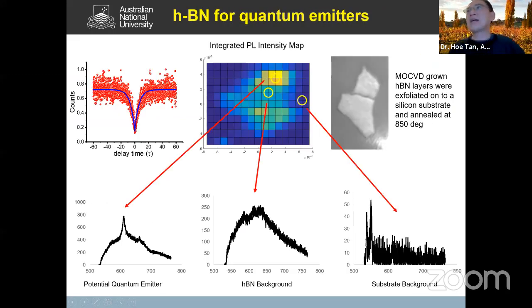But what we also discovered in collaboration with some colleagues from University of Technology Sydney, is that this impurity emission is actually not too bad. You know, you look at here, this is a piece of hexagonal boron nitride. Okay, so we map it out. And you can see these are very bright regions here, and some of them are not so bright, and this is outside the HBN.